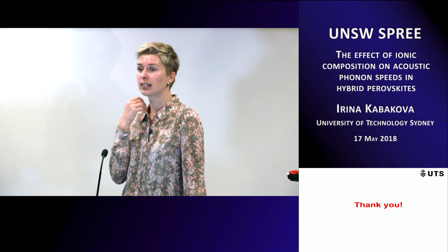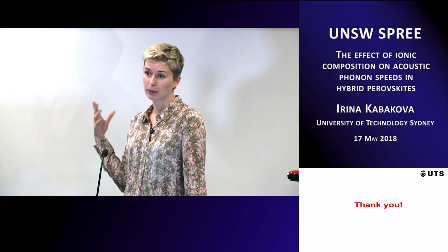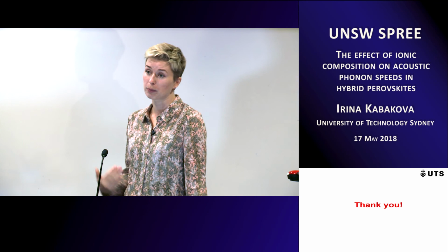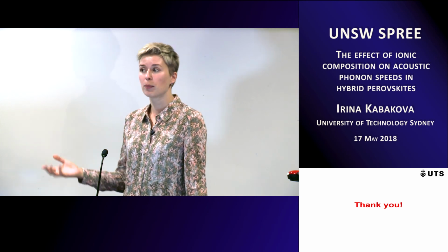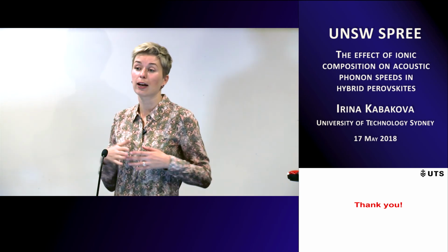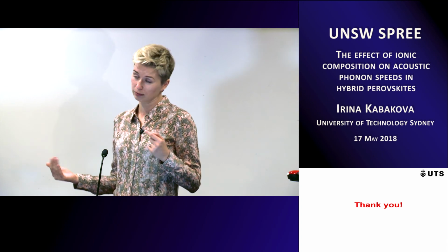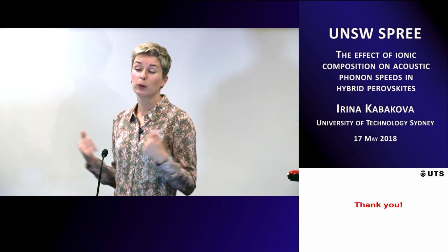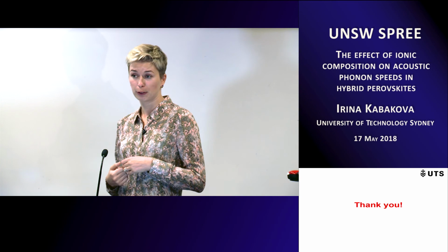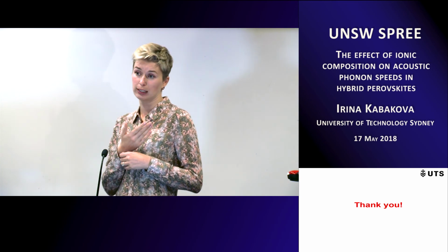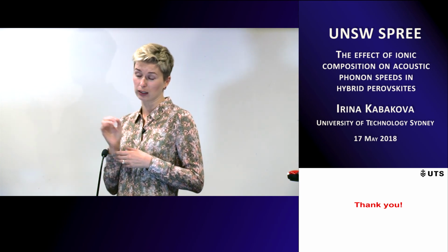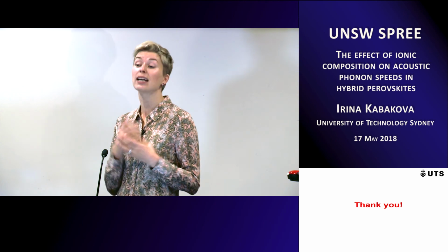You can change the excitation. Brillouin scattering is frequency independent. But it so happens that we didn't have a longer excitation laser. So that was a problem. You need to go to near-infrared for iodide because it absorbs everything in the visible. So they're quite dark. But you can do it.